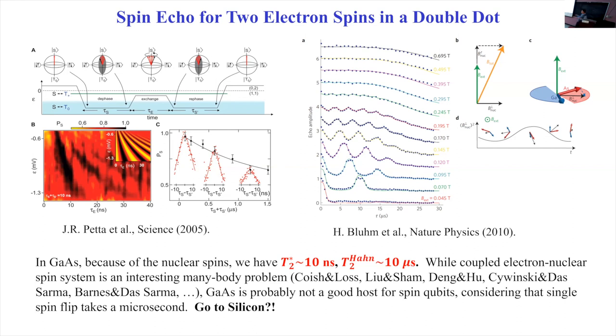And then even after you introduce spin echo to eliminate the quasi-static noise spectrum, the echo time is still only up to maybe 10 microseconds. I think in the original experiment, it was only 1 microsecond because of poor calibration and things like that. But later, in Amir Yacoby's group, it went up to 10 microseconds. Okay.